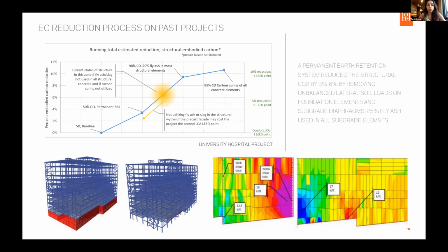So it wasn't that much of a jump in terms of embodied emissions to go from a temporary to a permanent system. What that did is that eliminated all of our subgrade foundation walls. It alleviated a lot of unbalanced lateral loads on our diaphragms, and it significantly reduced the thickness of the subgrade diaphragms. So that was a lot of concrete that was removed from the project by collaborating with the geotechnical engineer and seeing how better to manage geotechnical subgrade loading. So that got us from 0% to about 4%.